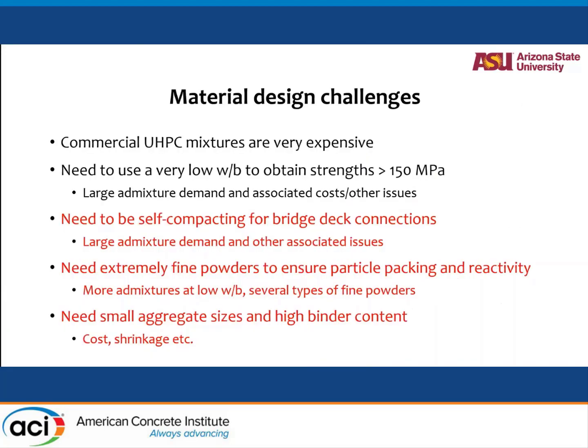The challenges with material design for UHPC have been told over and over again in pretty much every UHPC literature that you can see. Commercial mixtures are quite expensive. You need to have low water binder ratios to obtain strengths of greater than 150 megapascal, which requires a lot of admixtures, which adds obviously to the cost and other issues with compatibility between multiple admixtures. If you're using a water reducer, a set enhancer, a viscosity modifier, etc.